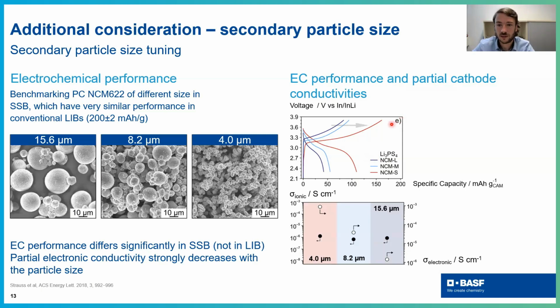And what you essentially see here is that you cannot achieve proper capacity if you take large particles around 16 microns. The charge capacity is below 100 milliamps per gram. The discharge capacity is below 50. It's very low. Then you move towards smaller particles, and at some point, the capacity is getting better. And why is that? This is actually very interesting.